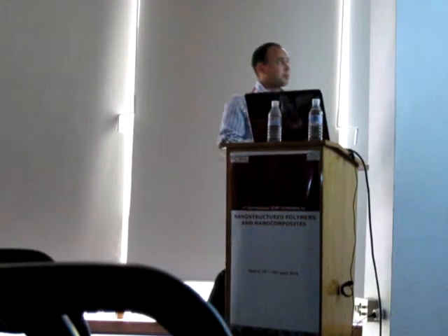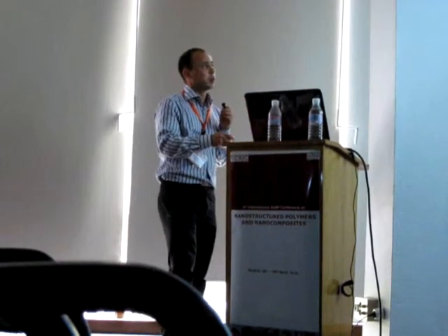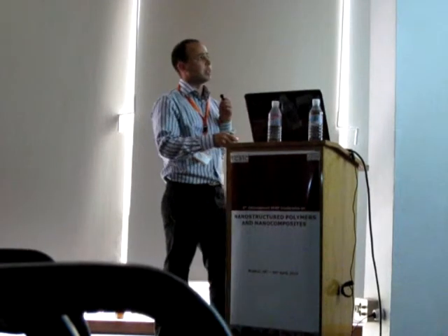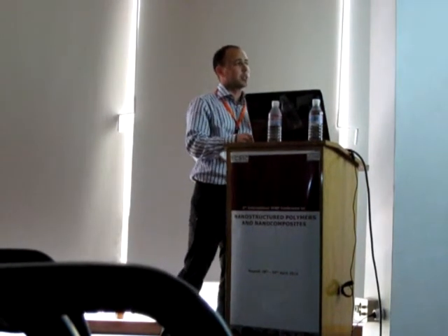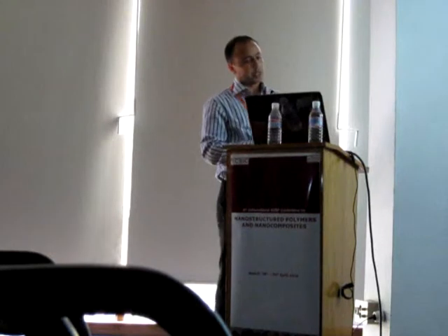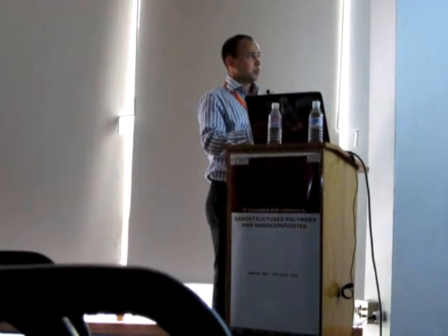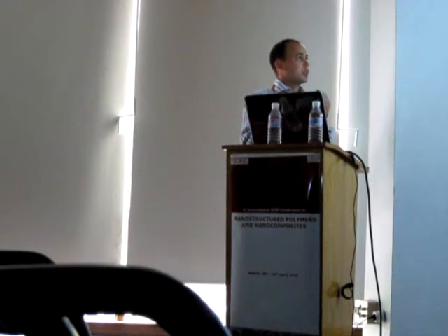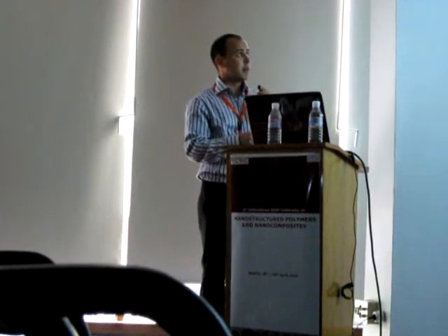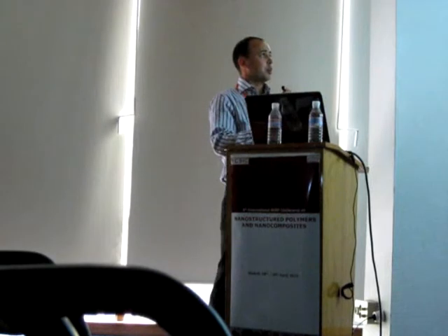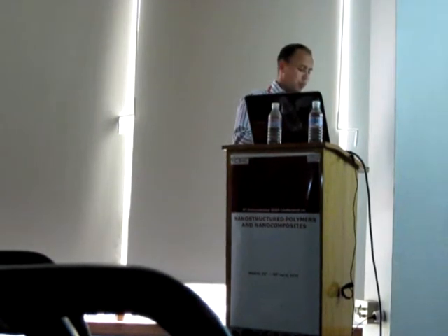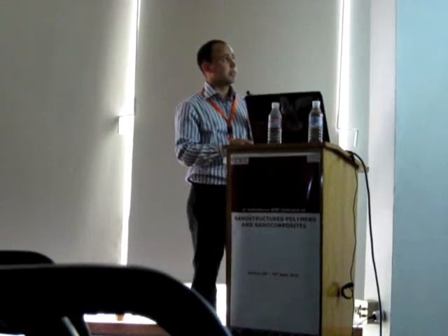And to finish, here we compare the calculated conversion rate using Ludovic software and the experimental conversion rate using the TGA GCMS technique. We remarked that for 10 and 20 weight percent of precursor injected, the model is operational, but with a higher amount of precursor injected, the model is not valid.